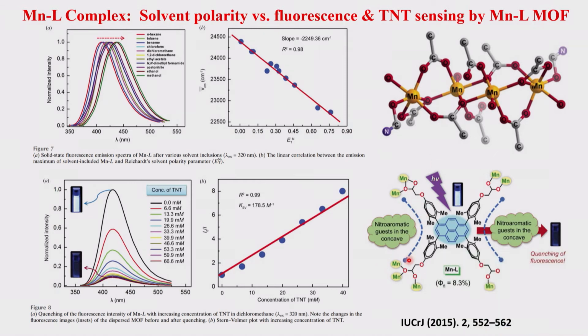So what is the second demonstration done in this particular example? If you take this particular compound, as I said, there is a crevice here where some molecules can interact. In this case, nitro aromatic guest species have been reacted with it, and many of them do not show much difference, but trinitrotoluene shows fluorescence quenching. If you have a small amount of TNT, there is less quenching. As you increase the concentration of TNT, the quenching increases.